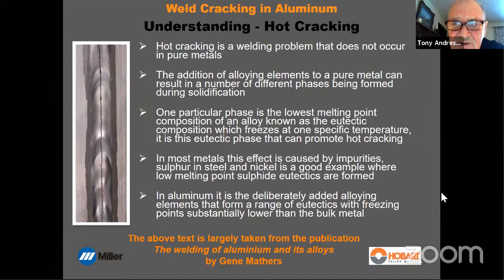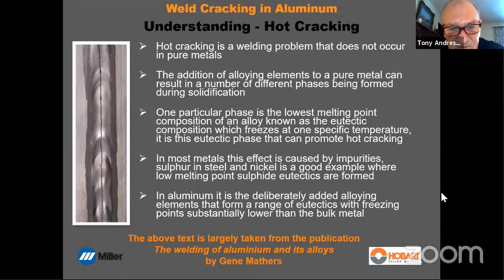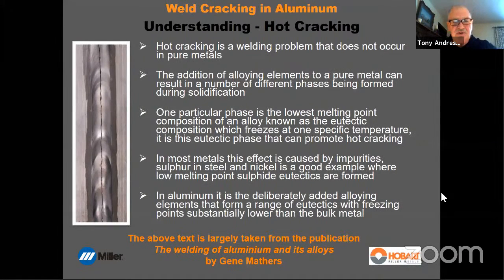Hot cracking is a welding problem that does not occur in pure metals. The addition of alloying elements to a pure metal can result in a number of different phases being formed during solidification. One particular phase is the lowest melting point composition of an alloy, known as its eutectic composition, which freezes at one specific temperature. It is this eutectic phase that can promote hot cracking. In most metals, this effect is caused by impurities. Sulfur in steel and nickel is a good example, where low melting point sulfide eutectics are formed. In aluminum, it is the deliberately added alloying elements that form a range of eutectics with freezing points substantially lower than the bulk metal. I think he did an excellent job in describing what's going on here.